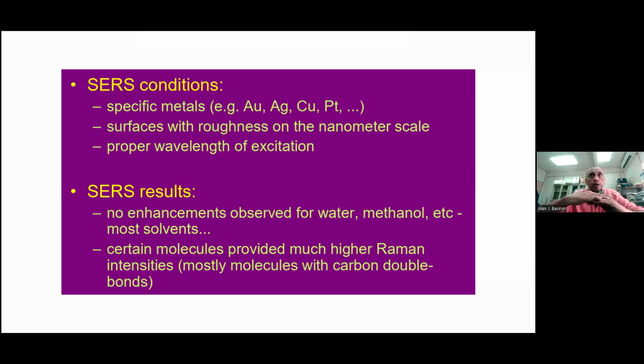Certain molecules provide much higher Raman intensity, mostly molecules with carbon double bond. So for example, when the molecule is not absorbed onto the metal, which can be gold, silver, platinum, certain types of metal. When the molecule is absorbed onto the metal surface, this molecule or this bond functional group absorbed on the metal surface will give you the SERS spectrum. So when water is not absorbed on the surface, then water cannot give you the enhancement.